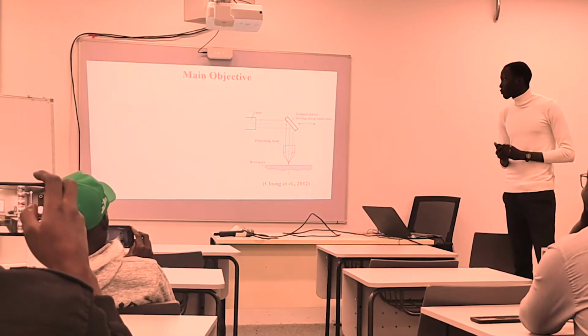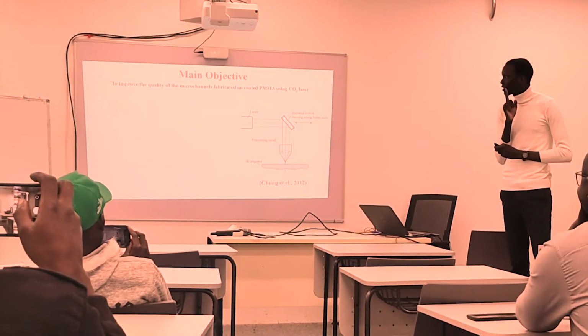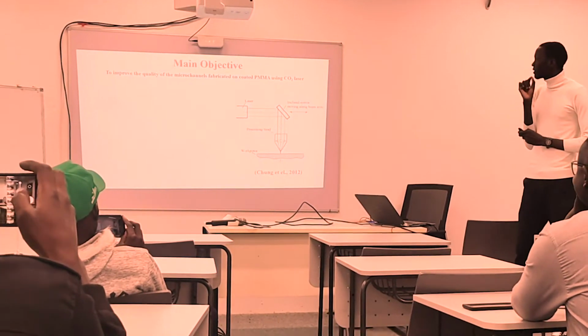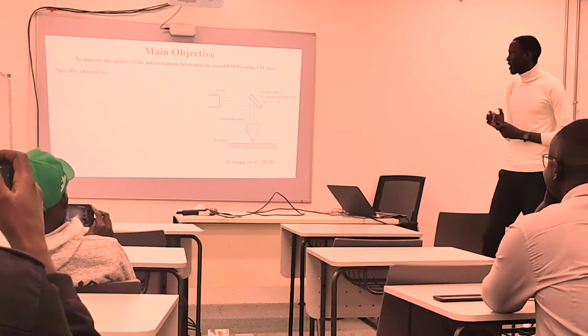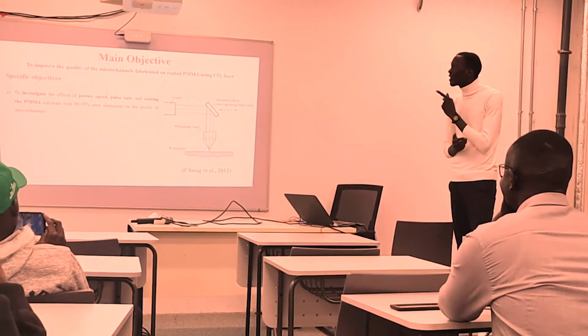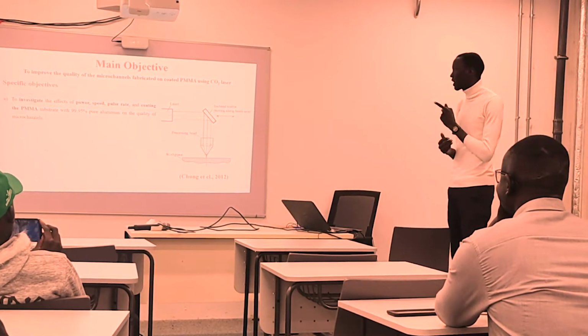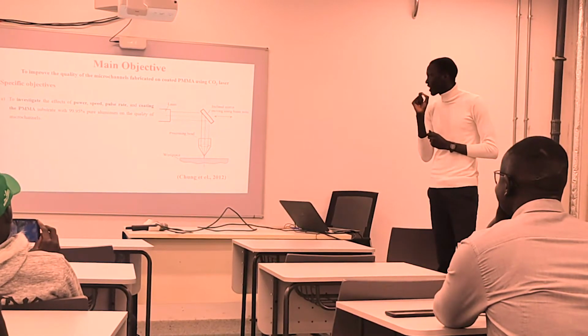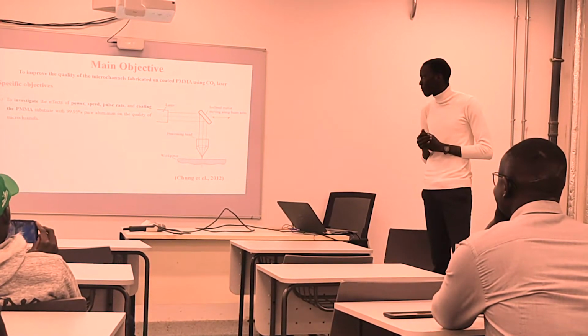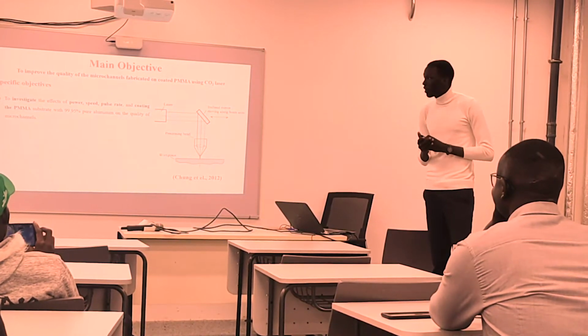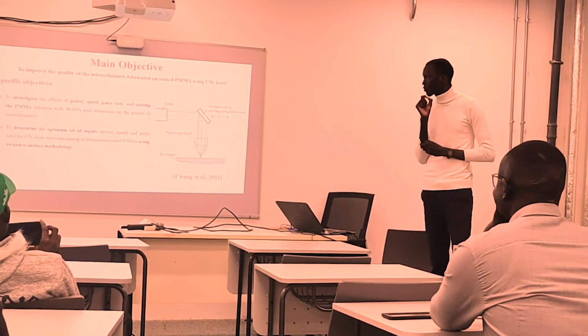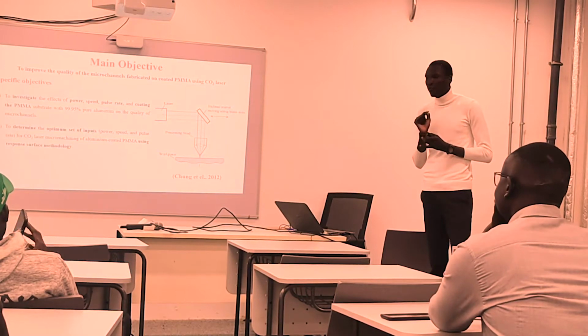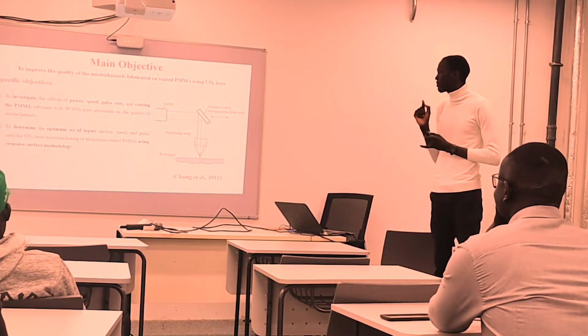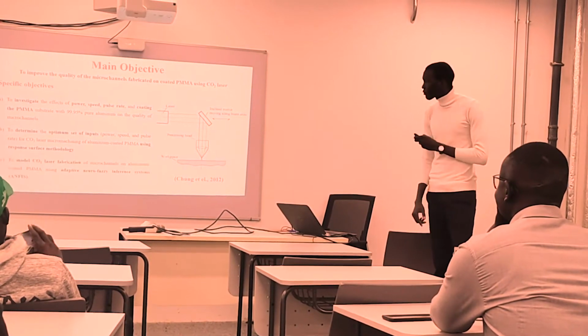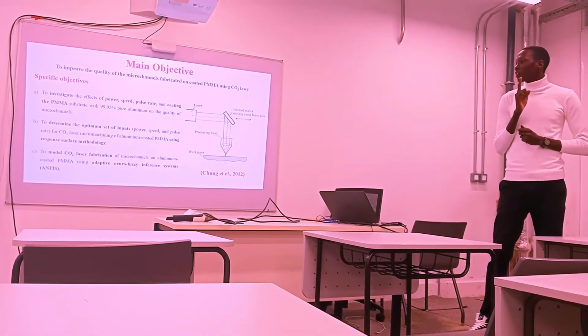Now, what is the main objective of this work? It is to improve the quality of the microchannel fabricated on coated PMMA using a CO2 laser. The specific ones are, number one, to investigate the effects of power, speed, pulse rate, and coating of the PMMA with 99.95% pure aluminium on the quality of the microchannels. Number two is to determine the optimum set of inputs, power, speed, and pulse rate, for CO2 laser micromachining of aluminium-coated PMMA using response surface methodology. The third one is to model CO2 laser fabrication of microchannels on aluminium-coated PMMA using adaptive neuro-fuzzy inference system.